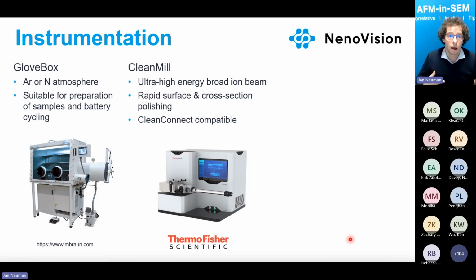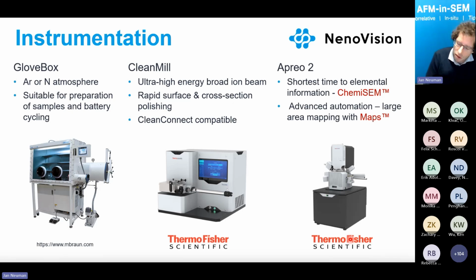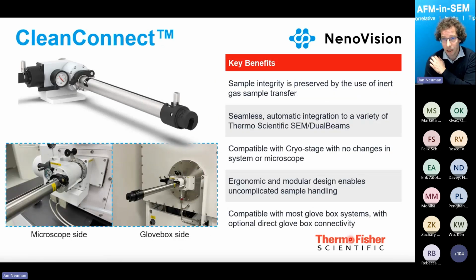Then we use a CleanMill for the broad ion milling, which provides different benefits like ultra high energy, rapid surface cross-sectioning or polishing. And on the SEM part, we use the Apreo 2 from Thermo Fisher Scientific, equipped with EDS and the AFM-in-SEM technology, enabling fantastic analysis of the surface composition. With the Clean Connect, as was mentioned, the key benefit is straightforward: you can use it to transfer samples from the glove box to the broad ion mill to your SEM or dual beams without any air exposure. It can also be used as a cryo stage.